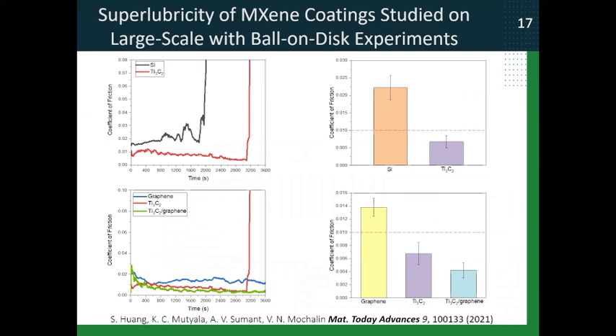So I have to tell you this first. When we tried to test these films in just ambient air, nothing interesting happened. They degraded fast and the performance was nothing impressive. But then when we switched to dry nitrogen atmosphere, we started to observe very interesting effects.